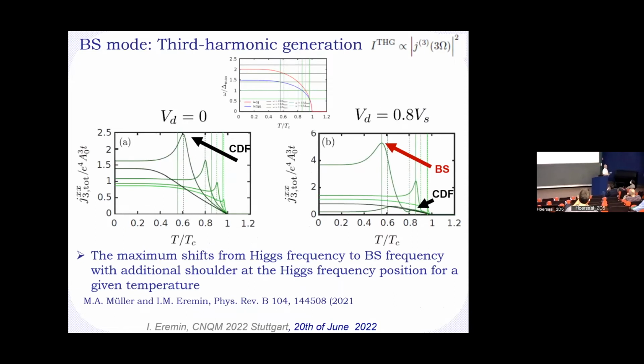Now, the first good news comes if you compare your third harmonic generation, for example, for parallel polarization of the field, where you look at the third harmonic generation current. Usually in experiment, you change it as a function of temperature, and what you're interested in is to hit the position of the Bardasis-Schrieffer mode and at the same time the position of the Higgs mode. So once you don't have a Bardasis-Schrieffer mode, everything is dominated by what is in experiment called the Higgs, but I believe that it's mostly dominated by the BCS response.